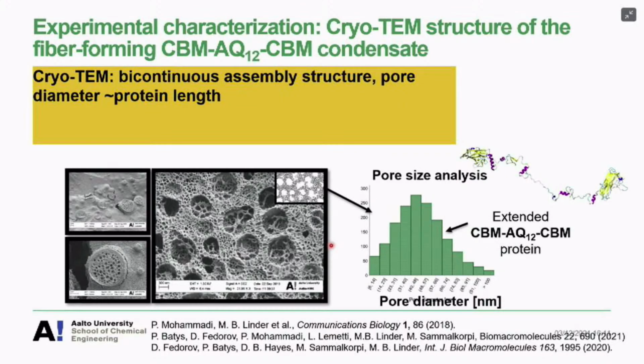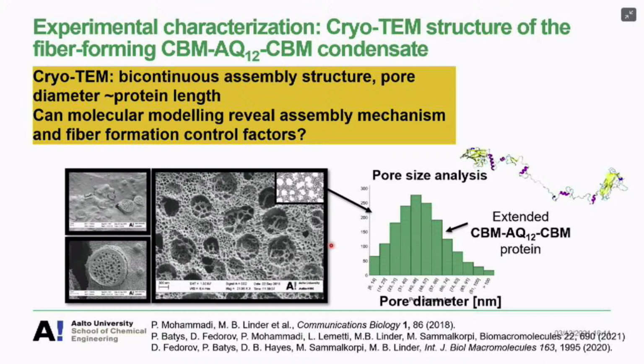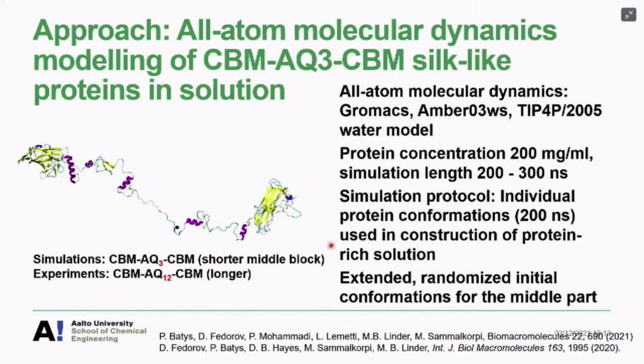So as already said, the cryo-TEM is showing a bicontinuous assembly structure, and the pore diameter is proportional to the protein length in the experimental system. The research question that I started answering in this field was: can molecular modeling actually reveal the assembly mechanism there and the fiber formation control factors? So we started modeling this via all-atom molecular dynamics simulations on a related protein construct, the CBM AQ3 CBM silk-like protein in solution. What you should notice here is that the simulations employ AQ3 and the experiments use AQ12. So there are more AQ blocks in the experiments than in the simulations. This is merely because the simulation becomes unfeasible if the protein is very long.